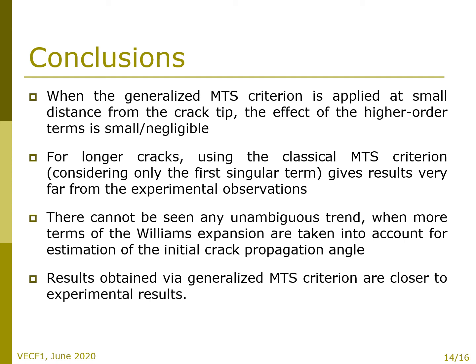There cannot be seen any unambiguous trend when more terms of the Williams expansion are considered for estimation of the initial crack propagation angle. But the results obtained via generalized MTS criterion are certainly closer to experimental results.